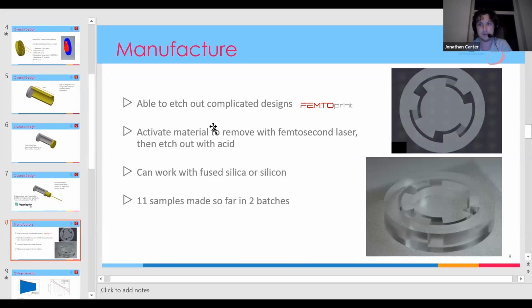So the first question was how to actually make these oscillators. The geometry itself is quite complicated, and we really needed a clever way of etching out the material between these bridges, these flexures. We contacted a few companies, but one was quite eager to do this, and that was the Swiss company Femtoprint. They have a method which allows them to work with fused silica, where they take your 3D drawing and work out which bits of the material in their sample they need to remove, and they activate these areas with a femtosecond laser.